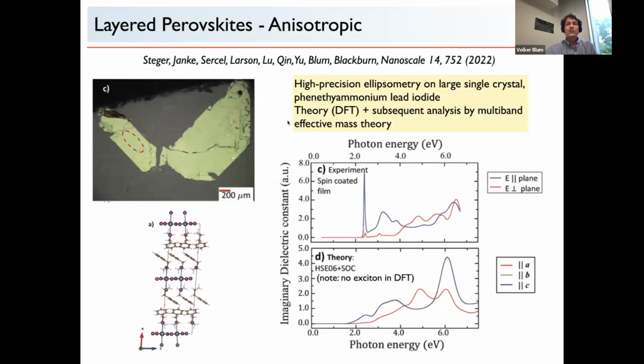We can do more. We can, for example, look at optical properties, and this is just a comparison of experimental versus computational optical properties of this phenethyl ammonium lead iodide. It's an anisotropic material, so it has optical properties that are different perpendicular versus parallel to the planes. We capture that in the calculations with the exception of the exciton. This is an excitonic peak, and that is not within density functional theory, but it can be captured by our collaborator, Pete Sercel, who can use our band structures and subsequently parameterize something called multi-band effective mass theory, which is traditional semiconductor theory, and get this.